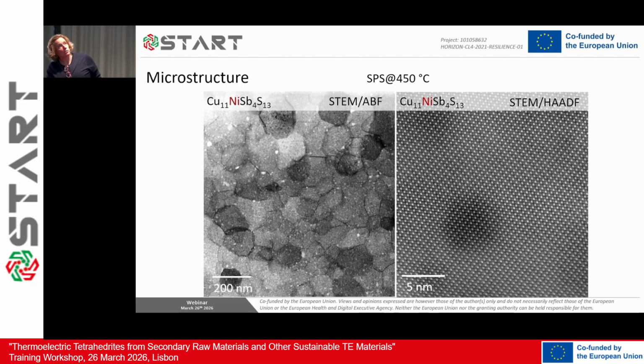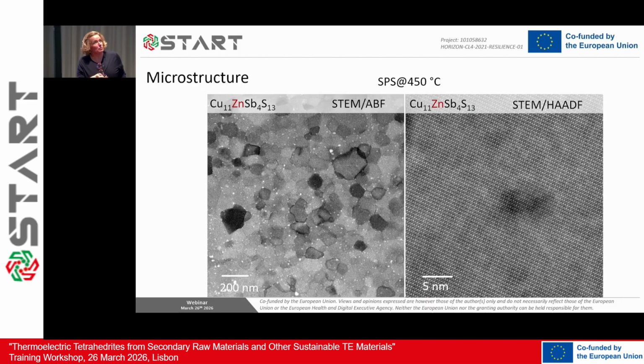So this is a pore, this is another pore, and you see that the sizes can go as low as 2 nanometers. All these little things you see here are pores, not noise. The same here, this is for zinc—you see exactly the same thing, and you see more things. You see this contrast here, this is also strange. There's probably a decomposition going on there, maybe a spinodal decomposition, because pure tetrahedrite has a decomposition. We see things there that are probably also indicating something like this.